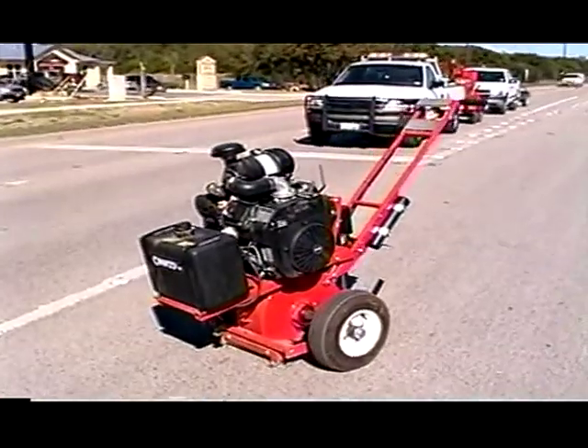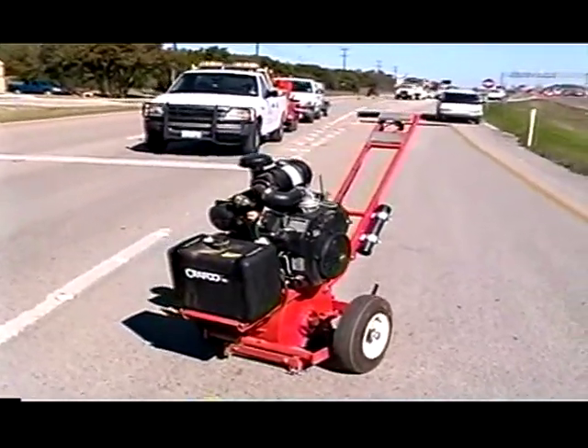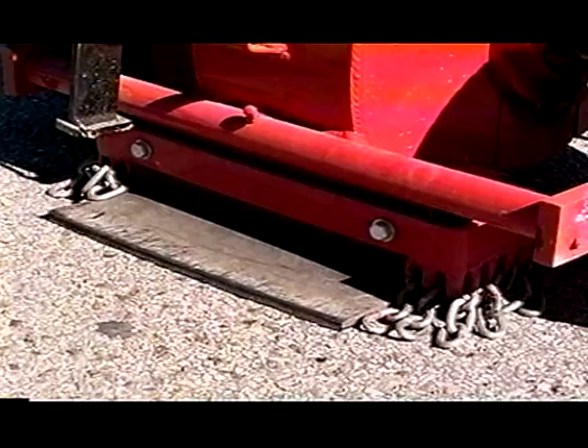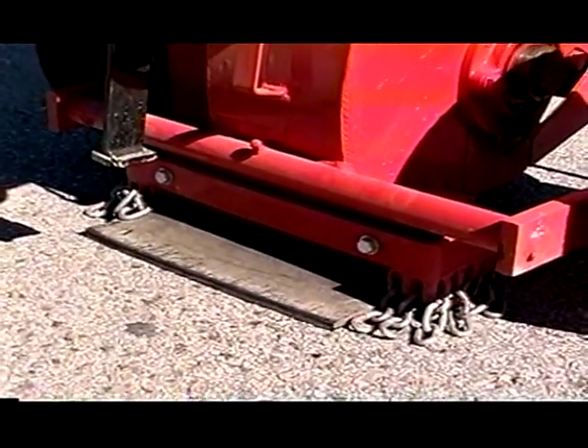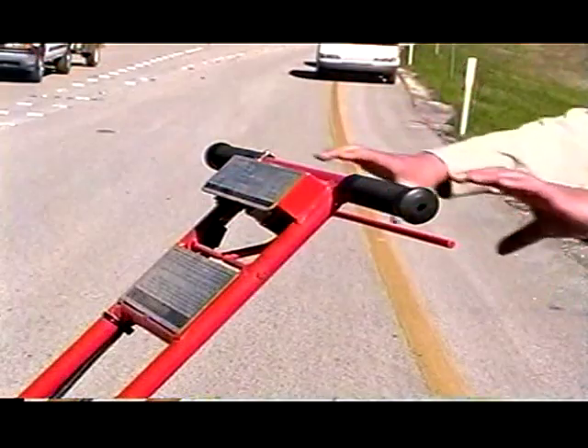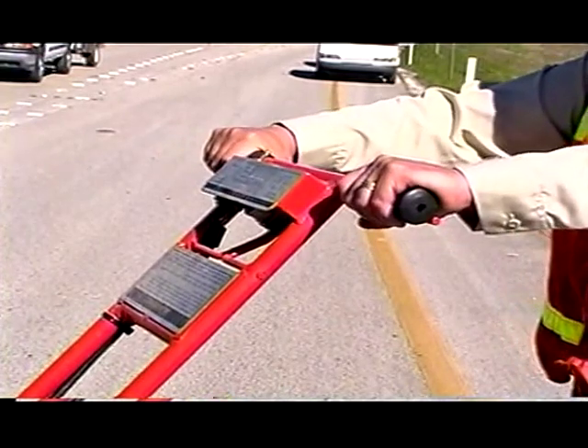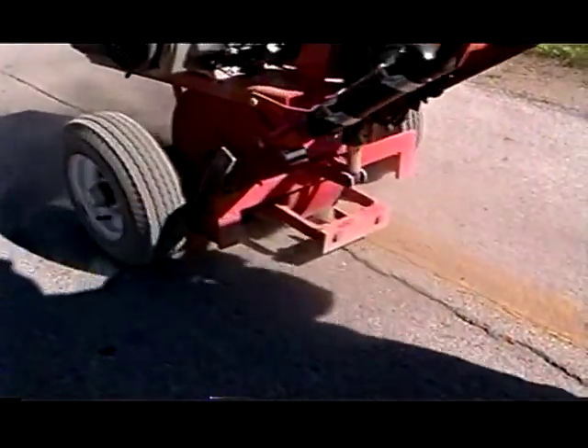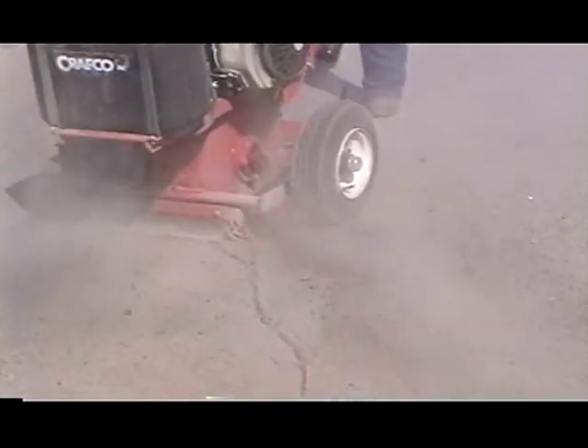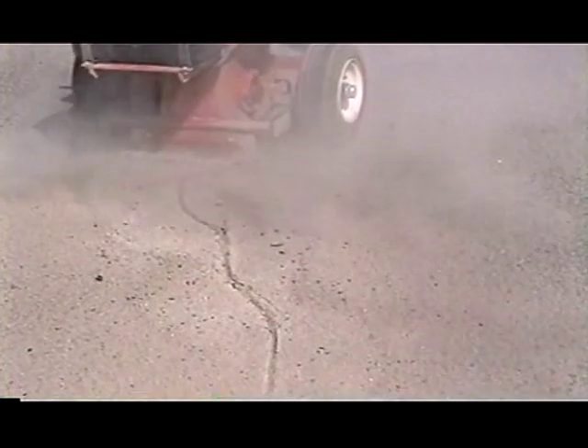The primary tool used in crack routing is the rotary impact router. To ensure safety, all guards and other safety mechanisms on the equipment must be functioning properly. During crack routing, caution must be observed to minimize damage to the surface adjacent to the crack. Routing equipment should follow meandering cracks, missing no more than 5% of the crack's length.